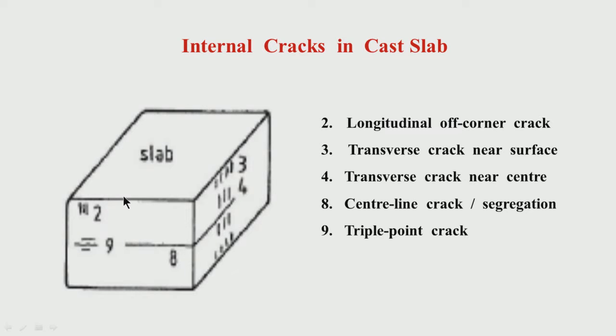Triple point means the solidification front: one solidification front generates from one surface moving to the center, another from the opposite surface moving toward that point, and from the bottom also another solidification front moves toward the center. All three solidification fronts meet at the triple point. This triple point — like the diagonal — is a relatively high-defect area because all the solidification fronts are meeting, similar to how grain boundaries normally have more defects compared to grain interiors.